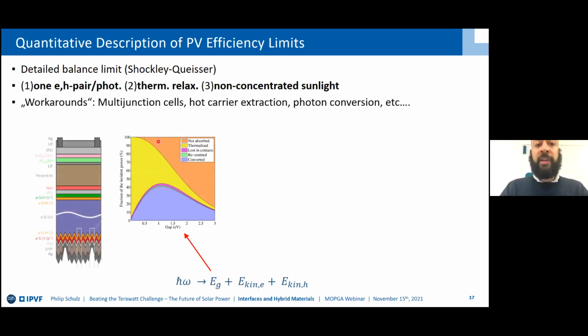Now the workarounds are, as I said, the multi-junction cells. On the left-hand side, you see one of those. This is silicon with a perovskite, a cross-section through these cells. There are a lot of different materials that are stacked together in this complex optoelectronic device, with a lot of interfaces that actually need to be perfected. And then, of course, there's the assumption of the band gap. With silicon, it's 1.1, as I said. For the perovskite, in this case, it's 1.6. And you see that now we are in different regimes in this plot to optimize the converted power.